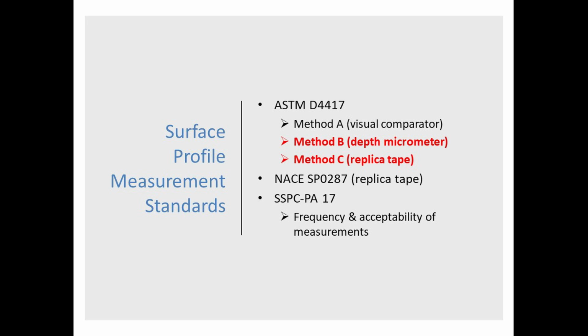ASTM D4417 is a standard for measuring surface profile. It tells us how to measure profile. It doesn't tell us what it should be. It doesn't tell us how many areas to check. It just says this is how you do it. It describes 3 methods. We're only going to talk about 2 here today. The depth micrometer, method B, and then the replica tape, method C. Those are the most common ones.